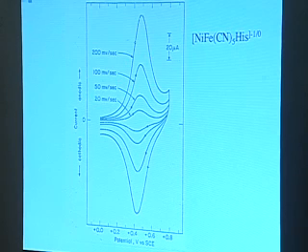And that peak width is a diagnostic for nearest neighbor interactions. On the surface, when we have things attached to a surface, they have nearest neighbors. Broadening of the peak means repulsive interactions. Narrowing of the peak is attractive interactions. So you actually can get narrower peaks.